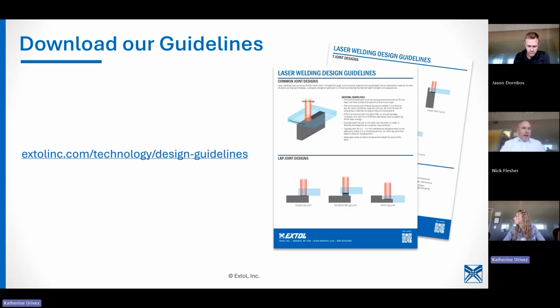Speed-wise, you're probably not going to actually beat ultrasonics, but it's pretty darn close. That really small device that Catherine showed, I think the laser energy on time was 1 second, and the depth was 0.2 millimeters. It's a more expensive technology than ultrasonic, but when you need it for those two reasons, you need it. Strength of ultrasonics to laser generally? I would say comparable. It depends on fillers and all those kinds of things, but we typically say design for 70 to 90% parent material strength.